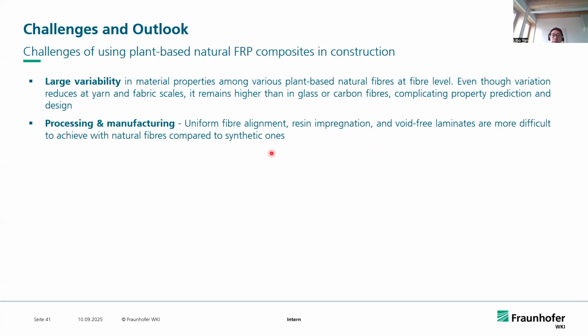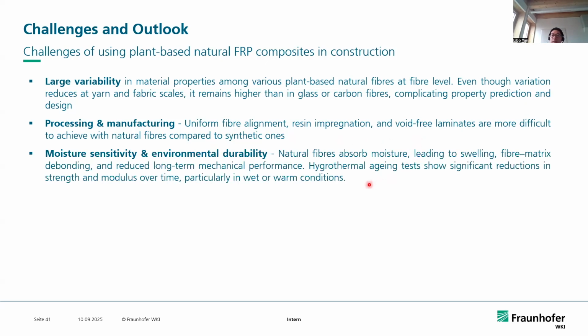Another problem is about the manufacturing. Compared with synthetic fibers, because of the hollow microstructure of natural fibers, it is typically hard to have uniform fiber alignment, resin impregnation, and avoid voids. And we know natural fibers absorb moisture, leading to swelling, matrix and fiber debonding. This could be an issue for synthetic fiber as well. But from the hygrothermal aging test, we see significant reductions in the strength and the modulus over time, particularly in wet and warm conditions.